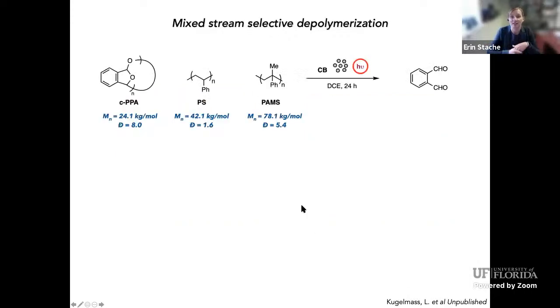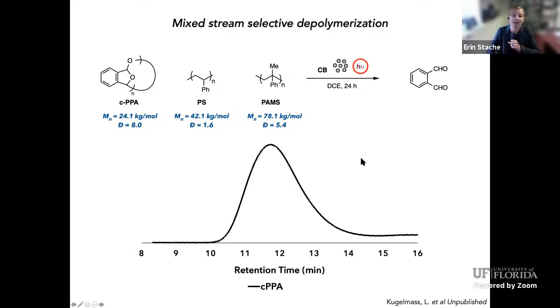And so lastly, the thing we're starting to work on now is selective depolymerization. Based on the degradation temperatures and the ceiling temperatures of these polymers, we should be able to hit a specific temperature gradient and get selective depolymerization. For example, cyclic phthalaldehyde decomposes at about 110 degrees C, whereas polystyrene and poly(alpha-methylstyrene) have much higher degradation temperatures. So if we mix all of these together in solution with the carbon black, we should only see depolymerization of the phthalaldehyde. And this is the phthalaldehyde polymer that we started with.